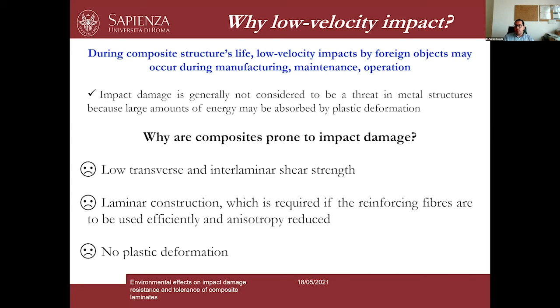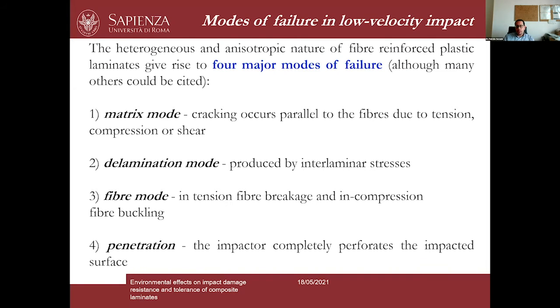Okay, so if we put together all these issues, we can easily understand why composites are so prone to impact damage. And basically, the brittle failure mechanism of a composite material, together with its heterogeneous and non-isotropic nature, gives rise to 4 major modes of failure under an impact event. They can be matrix mode, they can be a delamination mode, which are produced by interlaminar stresses. It can be a fiber mode or a penetration, when actually we get the final perforation of the specimen. So as you can see here, these different damage modes can be operative at the same time in a composite material. So the resulting damage scenario can be pretty much complex.